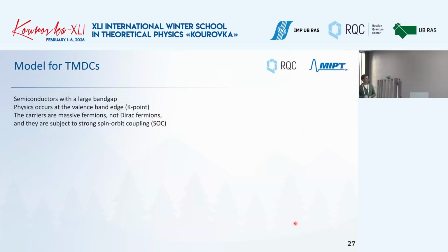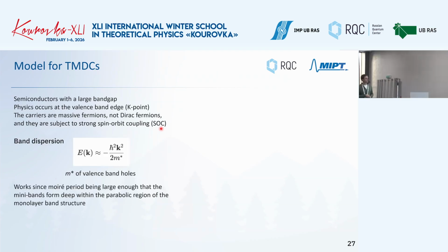And then you can guess, so what happens if you make a moiré potential with these two TMDCs? The difference is huge, because this is a semiconductor with a large band gap. So physics occurs at the valence band edge near the K point. And there, instead of carriers with very high speed, massless like in graphene, in this case their masses are huge, and they obtain some strong spin-orbit coupling. And the band dispersion looks like this. So not the dispersion as in the case of graphene.